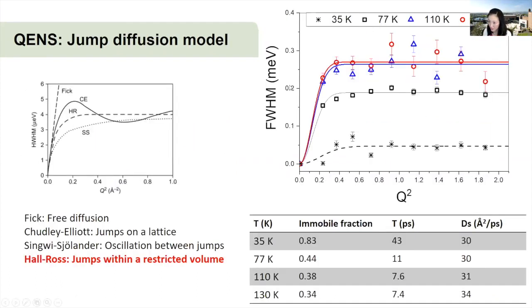And the broadening, the FWHM, tells how wide the peak is. The bigger the volume, the wider the QENS peak, and the quicker the hydrogen moves. So we can use a jump diffusion model to fit the full width at half maximum as a function of Q squared, and I found the HR model fits the curve best. Again, it confirms the hydrogen molecules can diffuse in a confined volume. From the jump diffusion model, we can calculate the diffusion coefficient listed in the table. So the QENS study quantitatively illustrates the solid-like and liquid-like hydrogen confined in pores over a wide temperature range up to 130 K, and the population of solid to liquid is temperature dependent. We can see that nano confinement really improved the thermal stability of hydrogen.